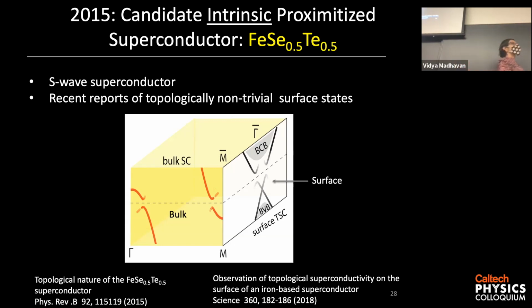Okay. So what we're trying to do is realize Majorana fermions in a solid state material. And like I said, one way to do it is to find a topological insulator which can be proximitized with a superconductor. As it turns out, this material does both. So iron selenium tellurium is a superconductor. It's been known for a long time as an S-wave superconductor. And very recently, in 2015 and 2018, it was suggested that this material may also be topologically non-trivial and may have these exotic linearly dispersing surface states on the surfaces.